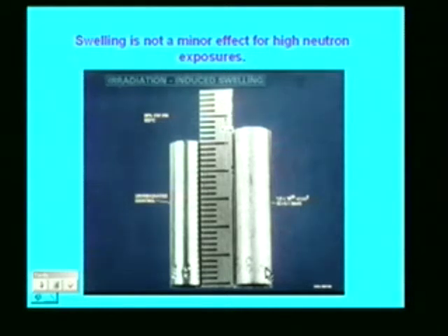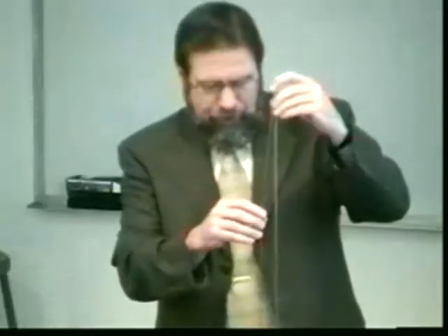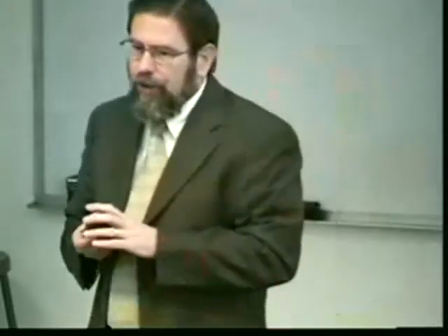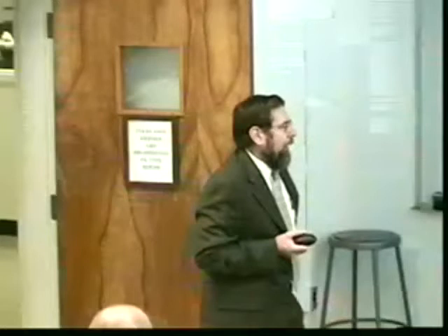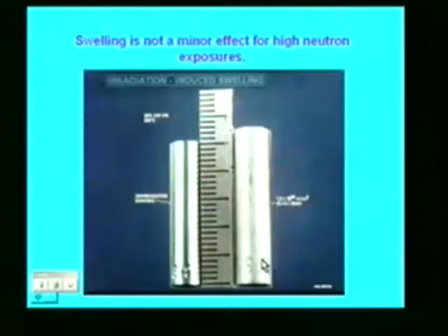Well, I've also heard people, especially in the fusion community, say that if you could hold swelling below 1%, everything would be fine. But let me illustrate that, because I have two rods. One is 0.3% longer than the other, which would correspond to a 1% volume swelling. And if I match the ends of these rods, this is how much it bows. So if we have even 1% swelling, for example, in fuel rods, there could be serious problems. Fortunately, there's another mechanism, radiation creep, that will sometimes help us by relieving swelling stresses.